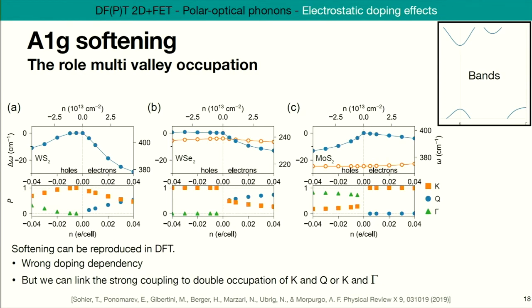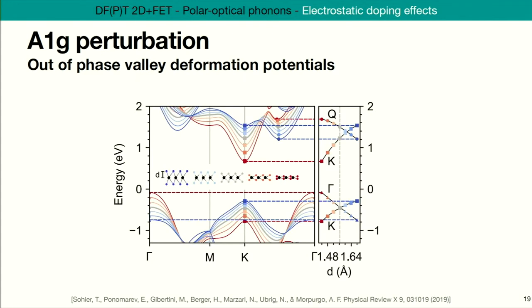Here we are there. But why does double valley occupation give strong coupling? That's still a mystery. And to understand this, we need to look at how the electrons and phonons couple in this material. And to do this, I'm going to go back to this relatively intuitive picture of the band structure moving as a function of the displacement pattern of the phonon. So this phonon, I said, is like a variation of the thickness of the material. This is what we see depicted here. So, the variation of the thickness. And here, we just compute the bands, the band structure of this material, for each configuration that we see here.